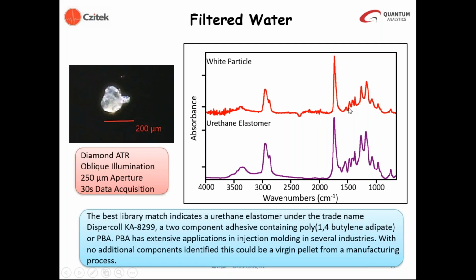And the spectrum of the unknown material is shown in the red at the top. This is the attenuated total reflection spectrum of that unknown particle. And you can see that it is well matched to a commercial material, trade name Dispercoll KA-8299, which is a two-component polyurethane sample that contains poly 1,4-butylene adipate. And this material has extensive applications in injection molding, injection molded products in various industries. So in this case, we could not find any additional components for this material. And it might be a virgin pellet from a manufacturing process, or it could have been abraded from a larger material before being collected from the environment.